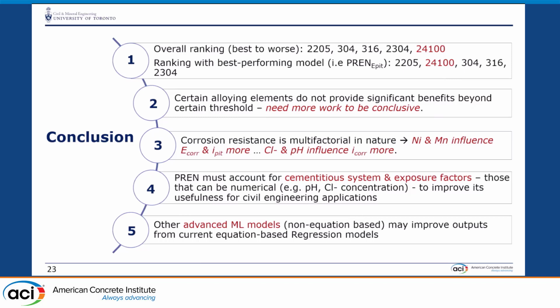The PREN number that we're looking at, we're basically concluding that it must account for the cementitious system and the exposure factors. In this case, we represented our cementitious system with just a change in pH. We understand that using mortar or concrete would change that. For exposure factor, we're simply limiting it to chloride and sulfates in this case. Obviously, with other models things can be improved, but the other models we considered don't have an equation to give. It's just a tool, and we need something that can be taken anywhere as opposed to something that can be seen on a website. So that's currently what we have.